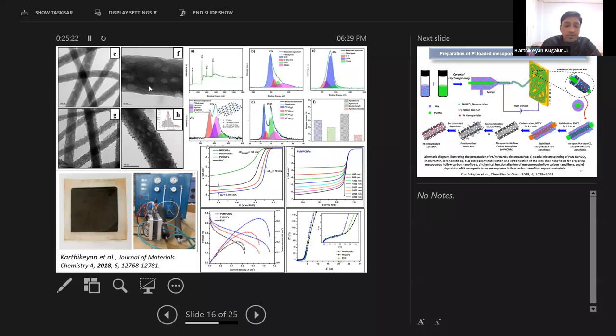And this is the magnified image where you can see the tiny pores present inside the carbon nanofibers. And these two pictures are showing the deposition of platinum nanoparticles. Because this carbon nanofiber acts as a support material for the catalyst, and the platinum acts as the catalyst material, the platinum is coated onto the carbon nanofibers, which act as a catalyst layer for the development of the fuel cell.